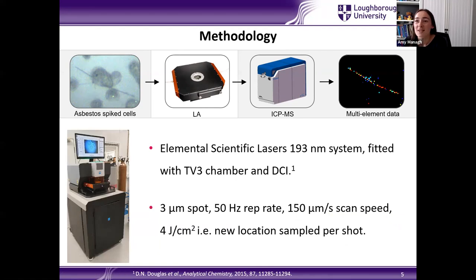Because of this increased sensitivity and speed, we're able to change the way that we do the laser ablation. We've been using a 3 micrometer spot size, a 50 hertz repetition rate, and 150 micron per second scan speed. This means that we were able to sample a new location on the sample surface with every laser shot. So we weren't using overlapping craters here. We were actually able to ensure that every time the laser fired, that generated a pixel in our final image.